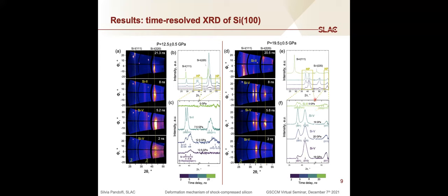And after full release, what's really interesting is that in this case, from higher pressure, we do still see traces of the lower pressure phase, so the silicon 2, down to 0 gigapascal. So it seems like the very fast timescale of laser-driven shock compression can actually extend the metastability domain of this high pressure phase, which is really interesting because it's different from what happens, for example, under static compression, for which silicon 2 during decompression normally back transforms to the ambient phase if at high temperature, or transforms to different metastable phases such as silicon 3 if at room temperature.